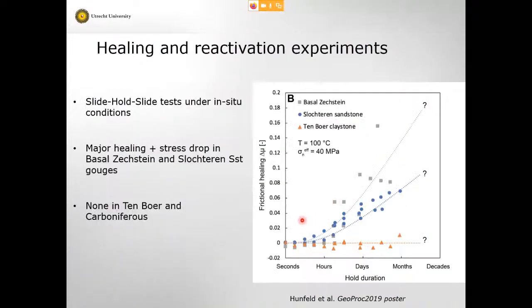Also looked at what happens if you slide these fault rocks and then stop and just leave them under in situ conditions in a so-called slide hold slide experiment, a friction experiment where you slide the rock, you let it heal at in situ temperature, then you re-slide it and you measure the increase in friction coefficient. So here's increase in friction coefficient after healing for different amounts of time. Interesting thing is that the clay-rich rocks show absolutely no healing, no increase in strength with time. They remain weak. The sandstone increases quite strongly in strength, and this carbonate anhydrite basal evaporite increases very greatly. And these are the longest duration hold experiments ever done, actually, around 3 months.